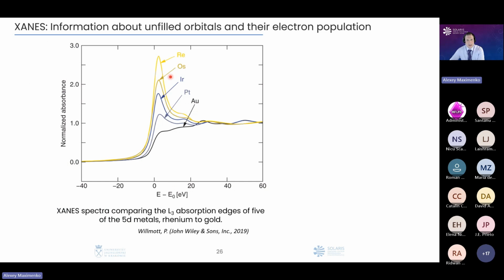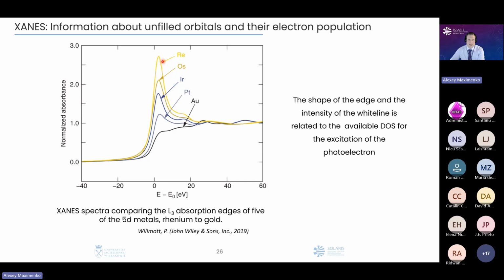Also, as I told you, using the XANES range, we could investigate the electronic density of states for electrons in our material. Here you could see, for example, how the intensity of the white line, you remember that the white line is, let's say, the most intensive point of absorption on your spectrum, changes when you have different atoms here, yeah? And by analysis of this intensity and the shape of this white line, you could investigate the density of states of the absorber atom in your material.